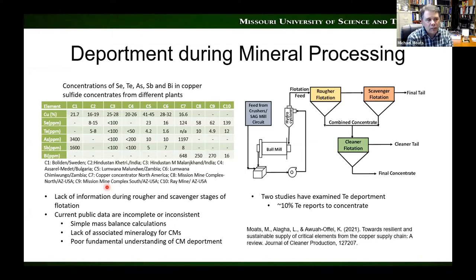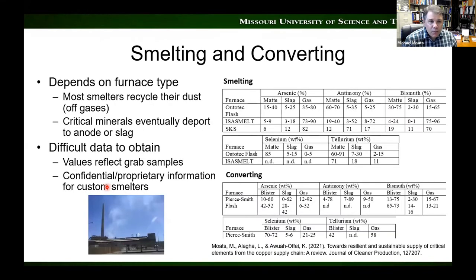We've done some work with the copper company to help understand deportment of some of these elements through their flotation, smelting, and refining. So I know some of the data exists, at least internally with companies, but from the outside looking in, it's sometimes hard to get at. So again, when we do have data, it tends to be not associated with mineralogy. They tend to be just grade. So we don't know where the arsenic, antimony, selenium, tellurium, bismuth, and so forth are all tied up. And there's really a kind of a poor fundamental understanding of why we depress it sometimes and why sometimes it floats. When the concentrate gets to the smelting, it's all over the map.